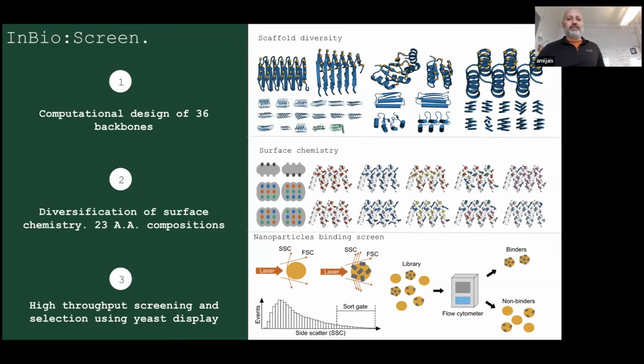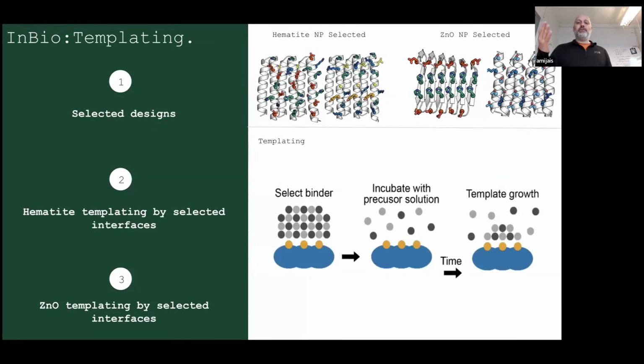So we designed about 35,000 proteins, and we expressed them on the surface of yeast. The idea then was to run them in a flow cytometer, which shoots a laser on each yeast individually, and you can measure the scattering. Let's mix the yeast with, say, zinc oxide nanoparticles, calibrate this a bit, and then run them through the flow cytometer. Because zinc oxide has a very different refractive index than water, we should see a difference. We did this and repeated it 3 times, every time enriching for things that had higher scattering. And then we ended up with these examples.